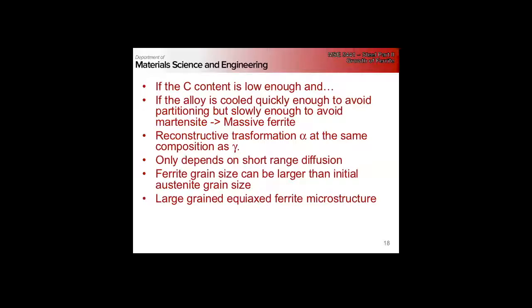Okay, and so when we have this massive transformation occur, we end up with ferrite grains that are larger than our initial austenite grain size. We typically won't have proeutectoid cementite, and we end up with a large-grained equiaxed ferrite microstructure.